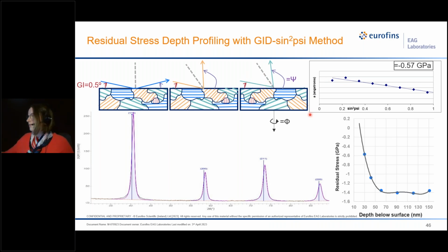Now, in this case, what we're plotting is the shift of each different kind of peak, which is going to shift in relation to each other because of, again, the stress. If you calculate the lattice parameter from each of these, it's going to be different based on where we've collected it, because essentially we're moving the detector, not tilting the sample. So these angstroms are your lattice parameter, and then we're going to plot that with respect to the tilt of the sample to calculate your residual stress.